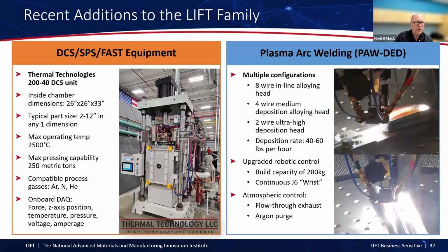Some cool recent additions. Two of the most recent additions to our high bay is first DCS or FAST or SPS, depending on where you live in the world. So direct current sintering is the most common term that we use inside of our organization. Some people would call it field-assisted sintering technology, spark plasma sintering. Either way, this equipment is stood up, and here we're running at roughly 250 tons and just on 1,000 amps of current that we pass through this to get to a max operating temperature of about 2,500 C.